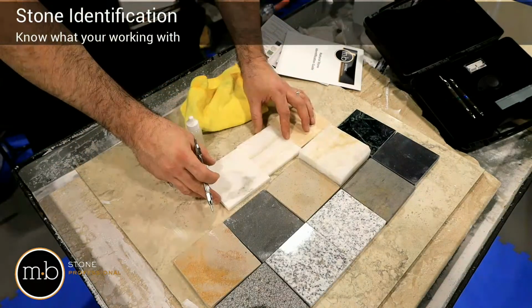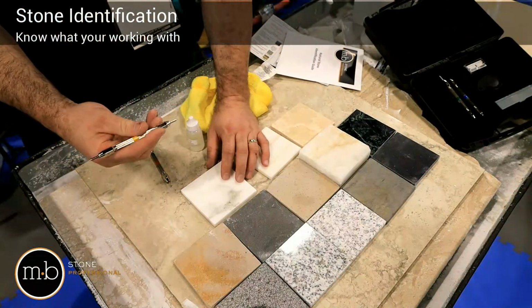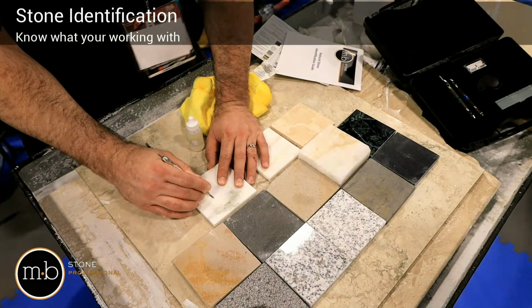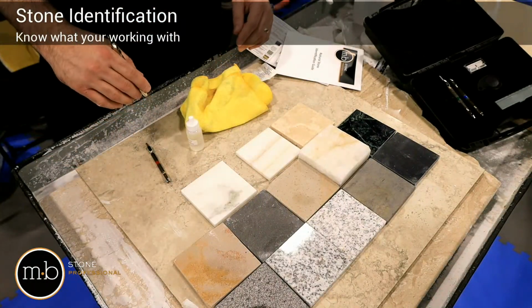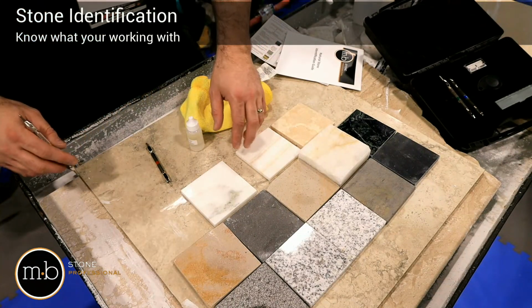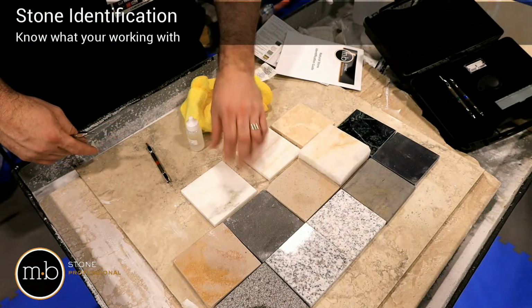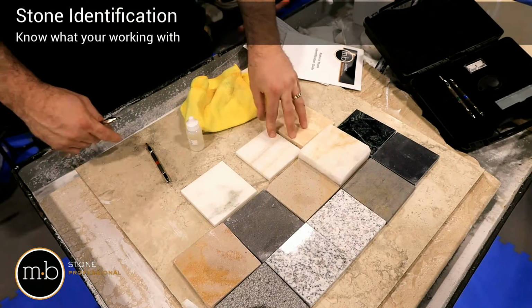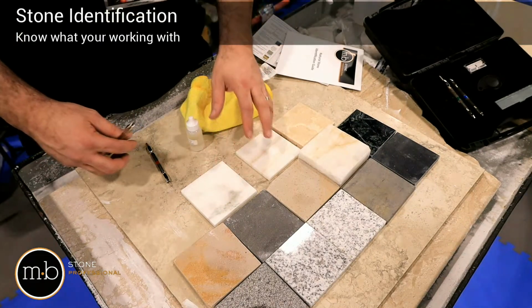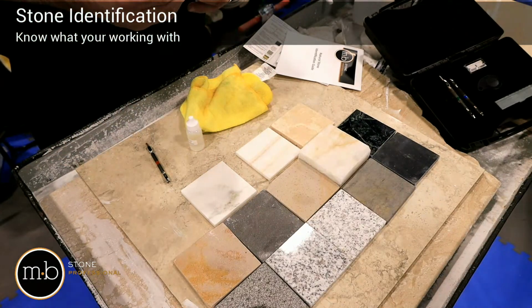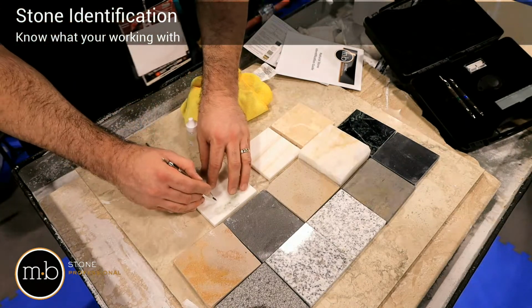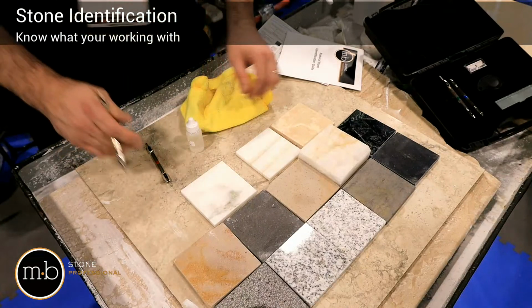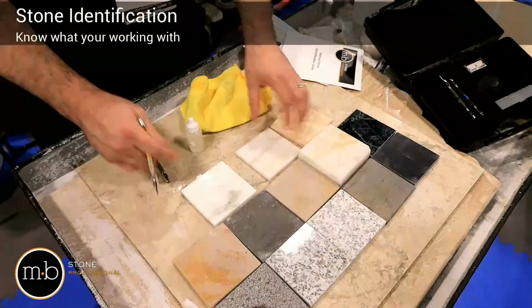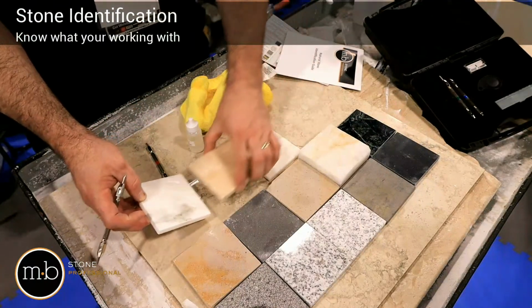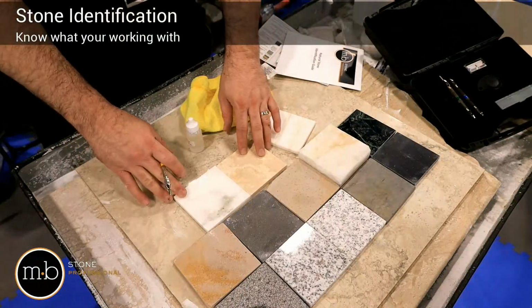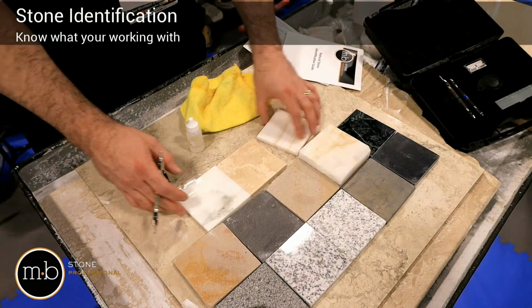The calcite, we'll start with a 5. And there you go. Most people would assume that this material is harder than onyx or travertine. And it is, but not by much at all. The number 4 even left a mark. So this has the equivalent scratch resistance as a piece of travertine.